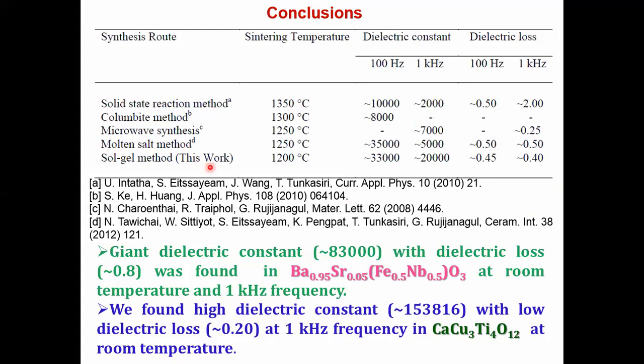When you dope with strontium, initially it was 33,000. Then we doped it with strontium, we got 83,000. And then we made another material, calcium copper titanate, which comes to 1,53,000 at room temperature, like that.